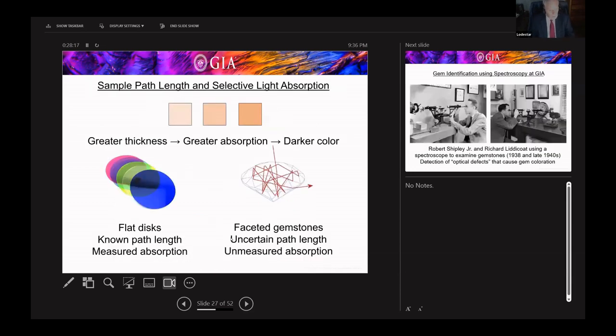Well, the path length through the gemstone is important. So if you have a greater thickness of material, you have greater absorption and a darker color. Now, if gemstones were flat discs, such as these pieces of plastic on the left-hand side, spectroscopy would be very easy. You have a known path length. You just measure the thickness of this flat disc, and you can directly measure the absorption.